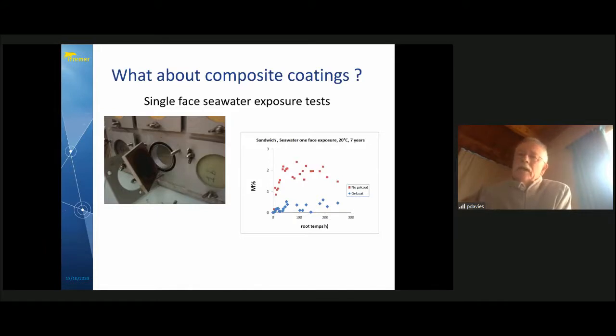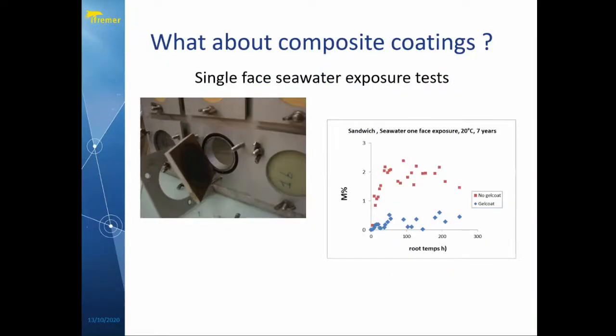You can see on the left here the setup. So we have the coupon here. There's an opening in a test tank, and inside the test tank there's seawater. So it's exposed, in fact, just one side of the specimen. So we're not worried then about edge effects, and we can just look at how the coating we're putting here is affecting the water ingress into the material.